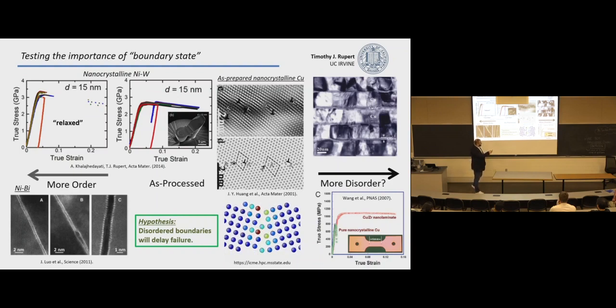As an example of why this might work, people have studied these relatively artificial microstructures where you deposit a nanocrystalline layer, then an amorphous layer made with solid state amorphization, then a nanocrystalline, then amorphous. And what people have found is that this more disordered layer type of structure can be stronger and more ductile. Okay? So this is our hypothesis, this idea that disordered boundaries can actually be a good thing and are going to delay our failure.